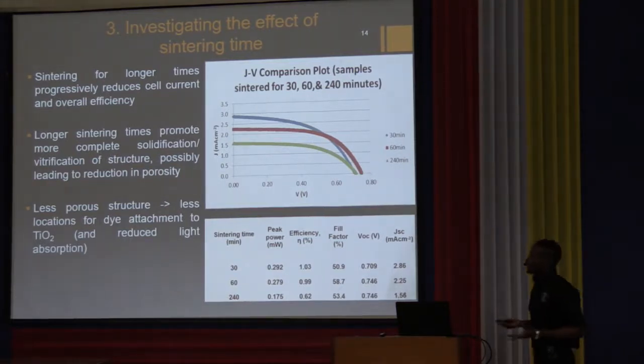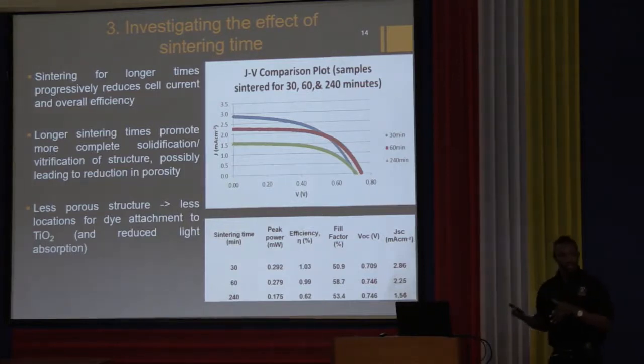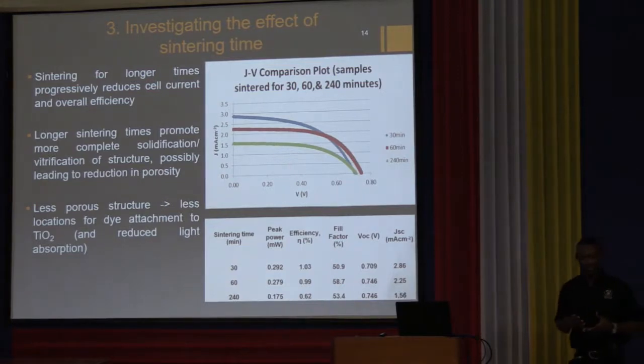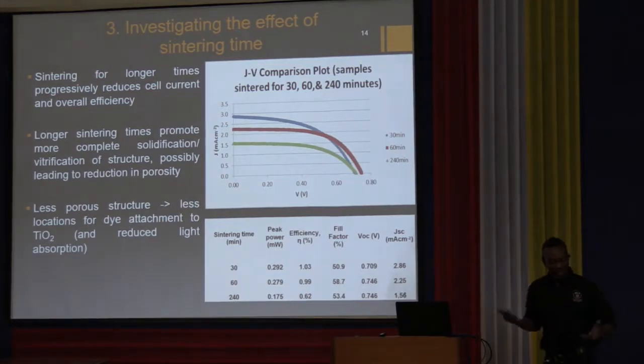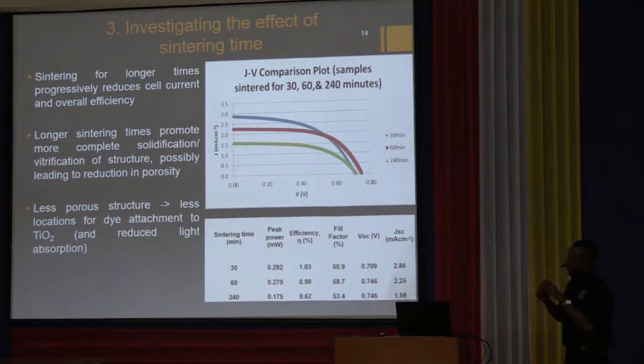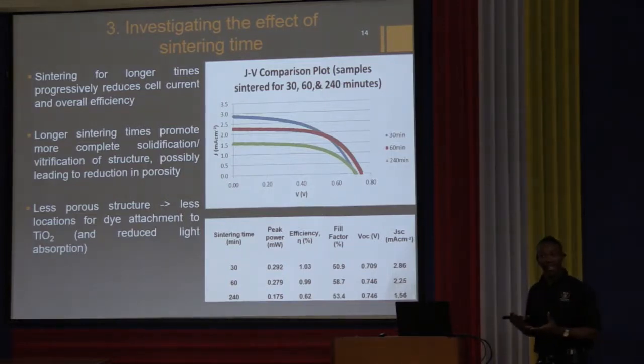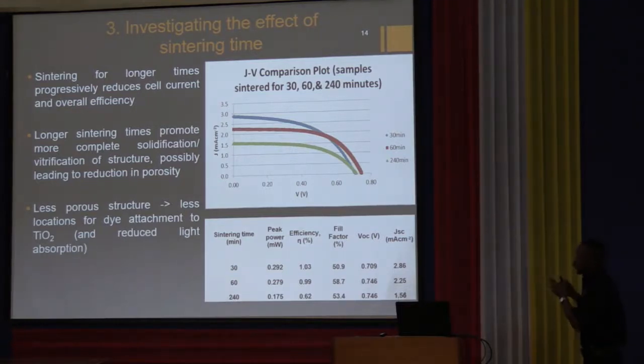Now, the rationale behind that is that the longer you sinter this material, the longer you bake it. If you've ever baked a cake and you leave it in the oven too long, instead of being soft, it gets hard. And I know this from experience because I've done it myself. All right? Not intentionally, of course. The longer you sinter is the less porous the structure is. So instead of having something like a sponge, you end up with something like a cement brick. This less porous structure means that it can't absorb as much dye. And because it can't absorb as much dye, then you get less current being produced.